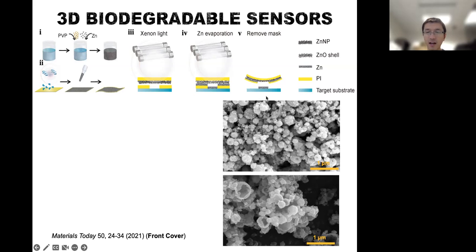and we shine the xenon light and the xenon light will create a localized heating and the heating will expand the nanoparticle in terms of thermal expansion. And zinc has different thermal expansion from the native oxide on the surface. So it will crack open the surface and zinc, with a lower evaporation temperature, will be transported through the cracked surface onto the target geometry and the zinc oxide will be left behind. So that helps us create a highly conductive zinc pathway and also to get that deposited onto different geometries.